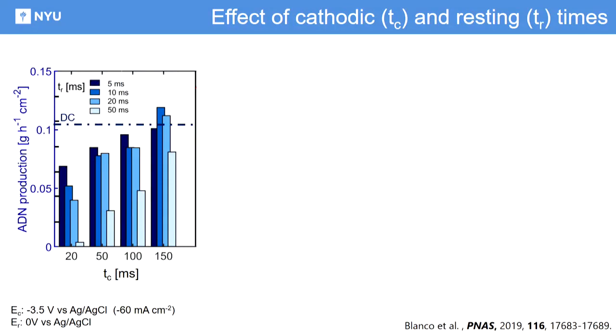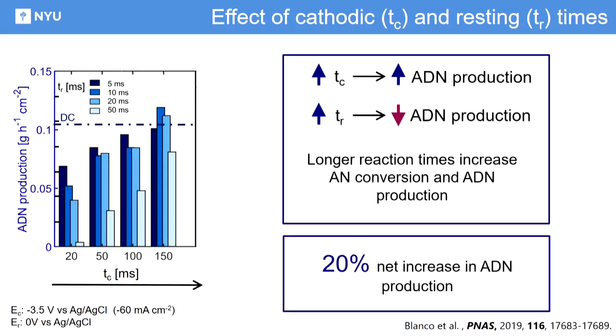So this is adiponitrile production as a function of cathodic times and resting times. And what you can see is that as you go to the right, to higher cathodic times, your electrode is active for a larger fraction of the time, so you produce more adiponitrile. For most cases, you produce less than in the case of DC, because your electrode is not active 100% of the time. But for some cases, you actually enhance the production rate of adiponitrile.